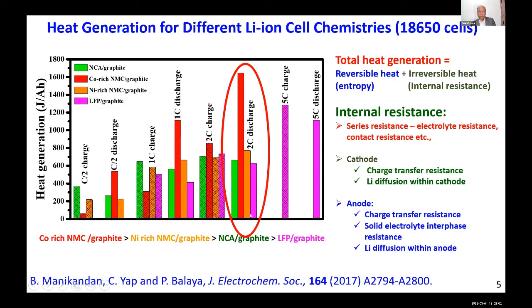So if you look at LFP graphite, that is the one which is generating low heat as compared to NCA graphite, then nickel-rich NMC graphite, then cobalt-rich NMC graphite. So cobalt-rich NMC graphite is not used in industry at all. People discard that, but it has its own interesting physics as well as chemistry, which I will not cover right now. Then if you go to 5C, which is 12 minutes charging and 12 minutes discharging, you can see only LFP chemistry can be charged and discharged in 12 minutes. None of these oxide chemistries works. That's why the LFP chemistry is highly robust as compared to the oxide chemistry.